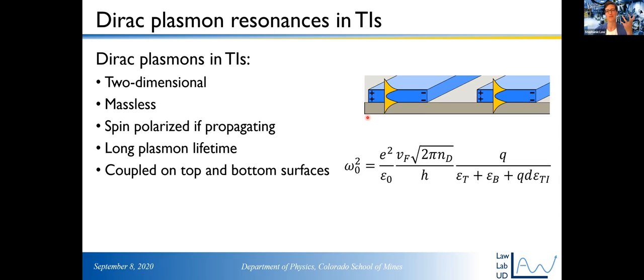So we have a 200 micron wavelength light and like a 200 nanometer film. What this means is that you're going to excite a plasmon polariton on the top surface, and a plasmon polariton on the bottom surface at the same time. And they're going to couple to each other. Just like coupled harmonic oscillators, just like we talked about, you get an acoustic mode and you get an optical mode. We can only see the optical mode because we do optical spectroscopy. But this is what we're interested in looking at.